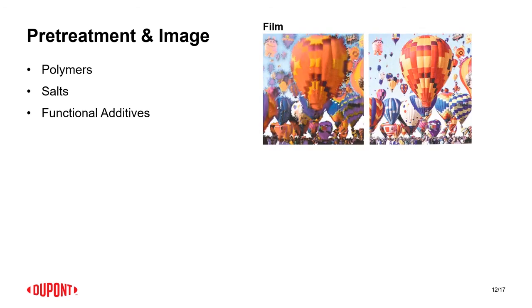And I think as we saw earlier, I forget whose presentation it was where they showed a sample of this, right? Again, this is some of our ink samples from the lab on film, right? And this is printed, I believe this is a PET film, right? You get a lot of running, but then if you apply a pretreatment, and in this case, it's a pretreatment that we're designing that's actually matched with the ink that's being used, you can do a lot in terms of your overall image quality, sharpness, and also durability, like the white ink you saw on the previous chart.